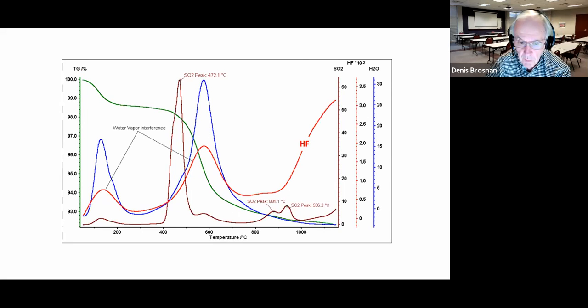In my laboratory, we can heat the clay sample in the simultaneous thermal analyzer, which gives the thermogravimetric axis here. The green line is the clay as it was heated up, and as you can see, once we got up to about 500 degrees C, we started losing weight. And HF is the red line over here. Here's the HF scale. And well, when the water was evaporating, we got a little bit of HF. I also used tap water here, city water, in this experiment. But nevertheless, you can see that we got a lot more HF as we went up in temperature to dehydroxylation.